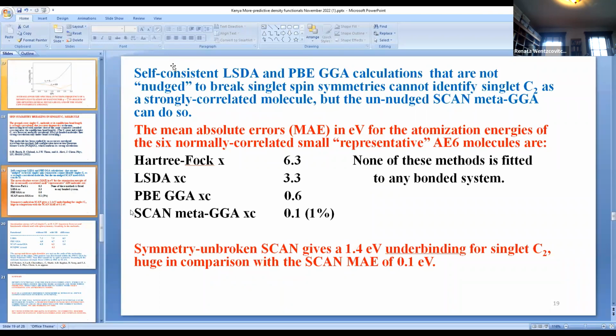In Hartree-Fock with exchange only, the mean absolute error is 6.3 electron volts. In the local spin density approximation, which includes correlation, the error is reduced to 3.3 electron volts, but that's still big compared to the strong correlation singlet C2. In the PBE GGA, the error is further reduced to about 0.6 electron volts, but that's only roughly comparable to the strong correlation. It's only when we get to the SCAN meta-GGA that the functional is accurate enough, making a mean absolute error of 1/10 of an electron volt, or 1%, much smaller than the strong correlation, so we can actually see that C2 is a strongly correlated molecule.